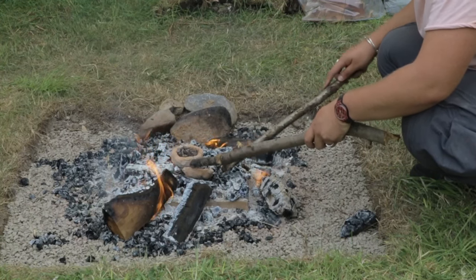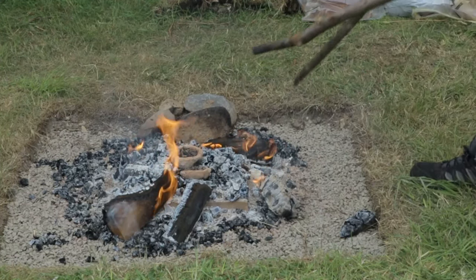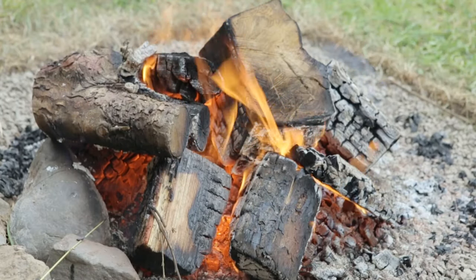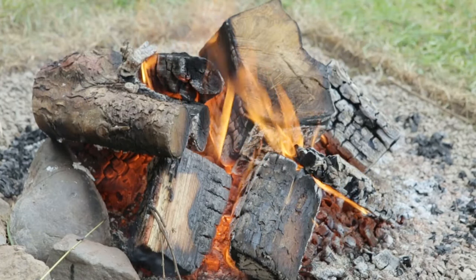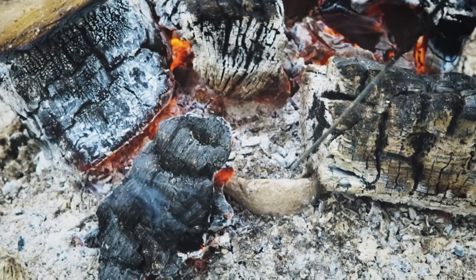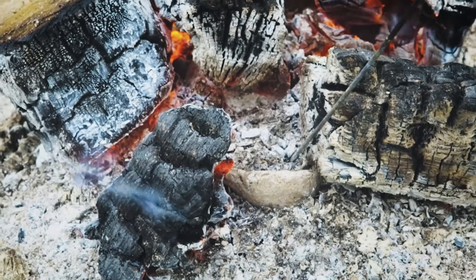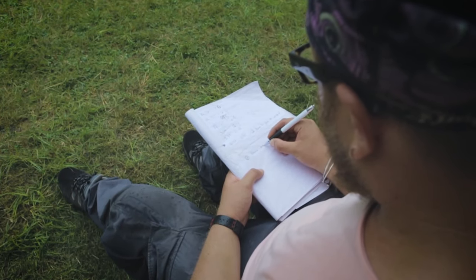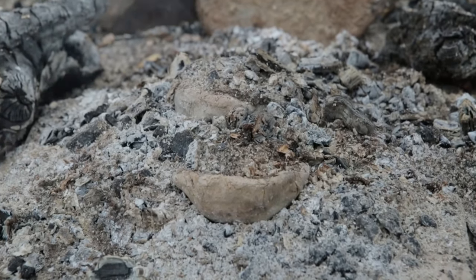We are now running the roasting with two crucibles and four logs. We constantly feed the bonfire and regularly check the temperature through our thermocouple, trying to relate the temperatures with the actual effects they will have on the physical status of chalcopyrite. After this phase, chalcopyrite should be ready to be smelted.